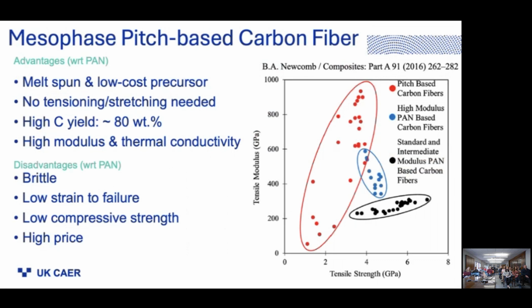Now, the advantages of the mesophase pitch-based carbon fiber is that it's melt spun and it's fairly low cost. PAN-based fiber has to be spun from solution, and pretty much the cellulose fiber as well. Melting and spinning is just far simpler. That's good. Also, no tensioning is needed during the thermal conversion of those fibers. So that's good. Extremely high yield.